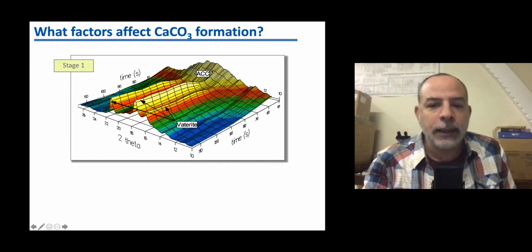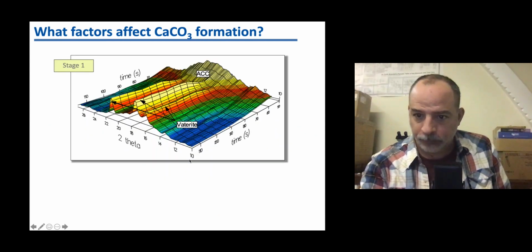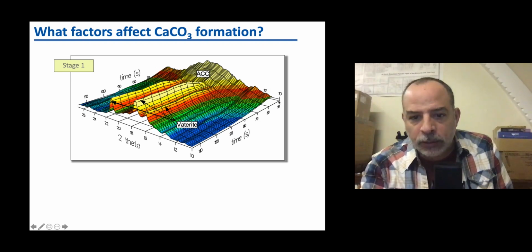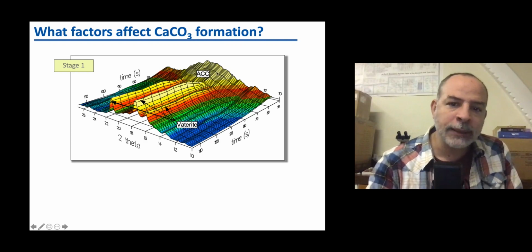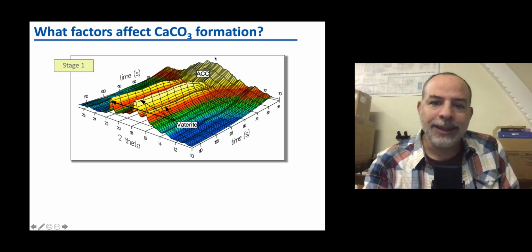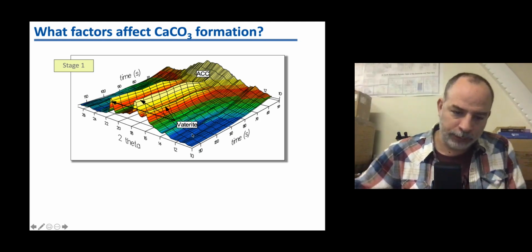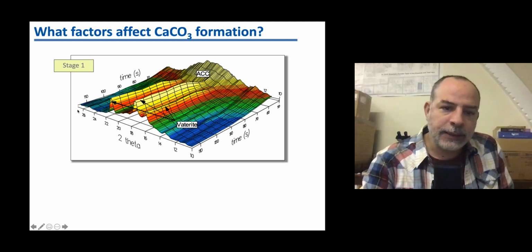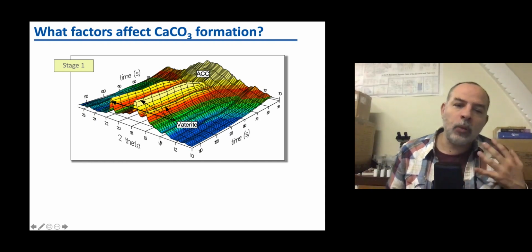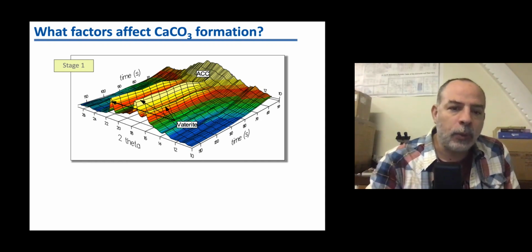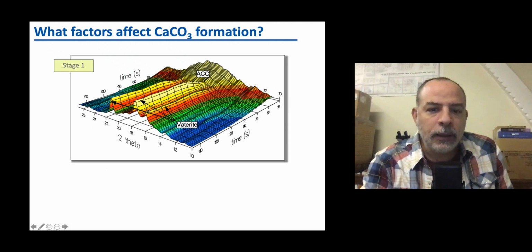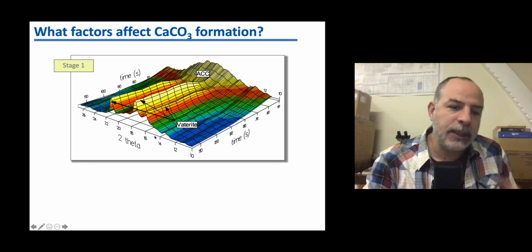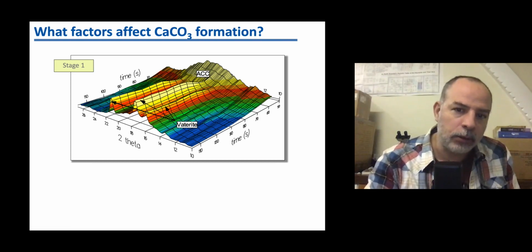So what happens here is that you see here this diagram, this is time. Here you have 50 seconds, almost 2 minutes. So in 1 minute, here what is happening is that you can see amorphous calcium carbonate decaying and forming one mineral named vaterite. Vaterite is a calcium carbonate polymorph. This axis represents 2 theta. If you don't know what this is, you only have to know one piece of information. Depending on the position of this peak, you can know which mineral you have. This is coming from X-ray diffraction, from the Bragg law, okay?